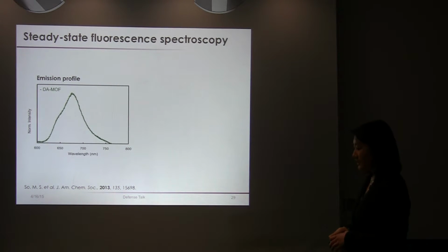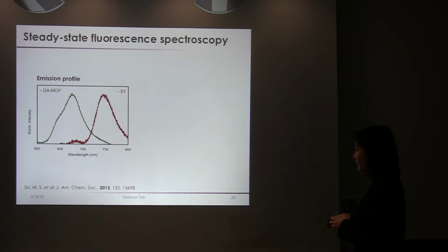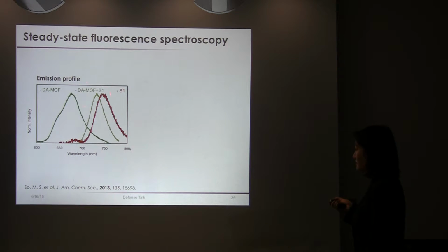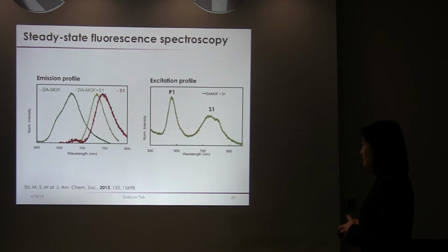And so in a 50-cycle LBL film, I would expect that if multi-step energy transfer were sufficiently rapid and efficient, then the emission from this DA MOF film would decrease while the S1 emission of the red absorbing dye would increase. And indeed, that's what I see when I deposit S1 dye onto the periphery of the DA MOF film. And furthermore, in the excitation spectra, I see that there are peaks at around 458 and 750, which are indicative of participation from both P1 as well as S1 when monitoring at the S1 emission. So both are participating light harvesters for S1 emission.